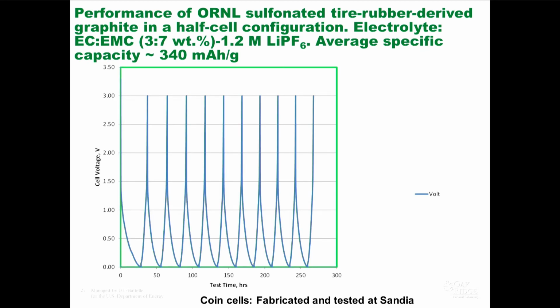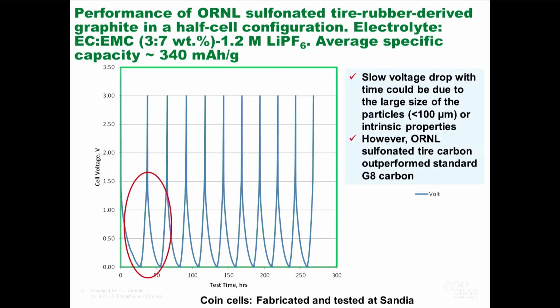And if you look at the voltage performance, here there's a slow voltage drop compared to the large. This could be either the large size of the particle or something intrinsic, because I said it's forming some composites more in the form of mesoporous. So we are still working on this, and this is an issue, something we want to change, because our particles were too large, and we found a method. I am going to talk about how we can grind it and get to the small particles.